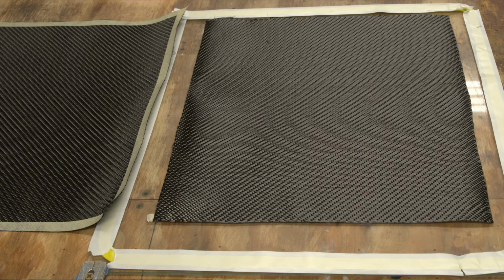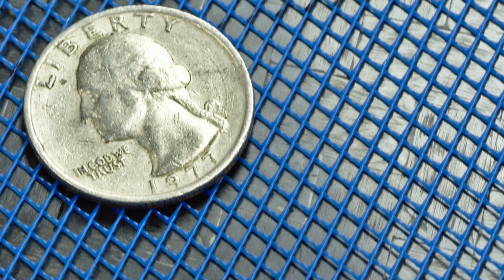Let me talk a little bit about the layer stack that I have been using. As I mentioned before, I've been using 2-ply of the carbon fiber, and I don't think I mentioned it's 200 grams per square meter weight on that fiber, so it's pretty thin. And once you get it cured, it's around 20 mils thick, so about 0.5 millimeter. On top of those 2 layers of carbon fiber, I put a layer of peel ply, and then on top of that, I put a layer of flow media. Everything I had seen up to that point said you need flow media to help that epoxy flow through when you're pulling the vacuum and pulling the resin through the sample. The flow media I have been using was this blue mesh, with very large square openings, and it's a little over 1 millimeter thick, so about 44 thousandths, roughly in that area.